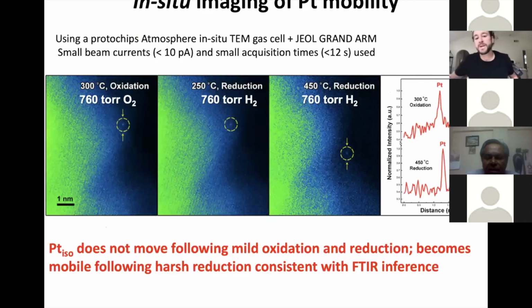So we then wanted to see, when we're putting platinum in these different environmental conditions, oxidizing, reducing, harshly reducing, is the change in its oxidation state coming from just breaking local bonds, or is platinum becoming mobile and moving around on the surface? And so what we found is, by doing in situ electron microscopy experiments under these environmental conditions, the platinum itself doesn't seem to move. This bright spot is our platinum species, single atom on a titania lattice. It doesn't seem to move between oxidizing conditions and mildly reducing conditions. But once you put this in hydrogen at high enough temperature, the titania surface itself starts to reconstruct, and so the platinum atom becomes mobile. So any changes in coordination environment that happen between these two states are likely local bond breaking. Any coordination environments here are likely because platinum has become mobile and started moving around.